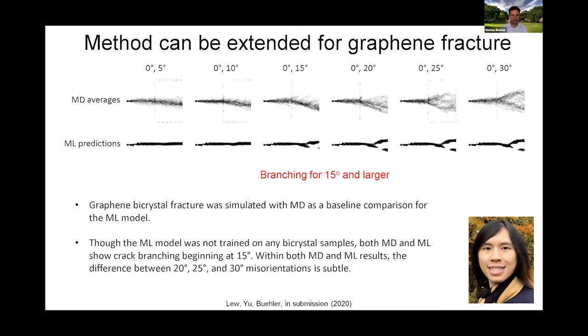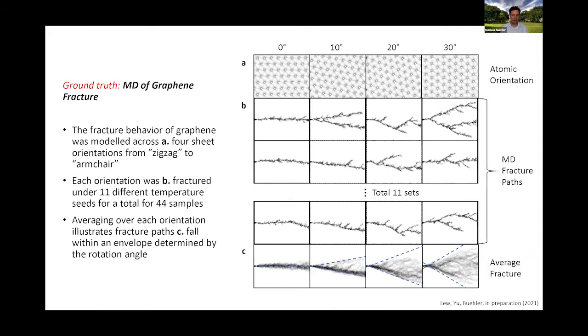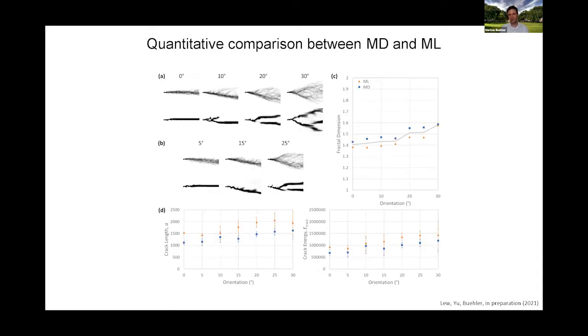The microstructure is more complex, and we have different chemical complexities involved here as the bonds break and stretch. And we've been able to show for that system as well, we can train a neural network very well again here and predict fracturing processes. You can see the MD fracture paths and the average paths, comparing the observation between MD and machine learning. They agree very well and essentially validate the predictions.